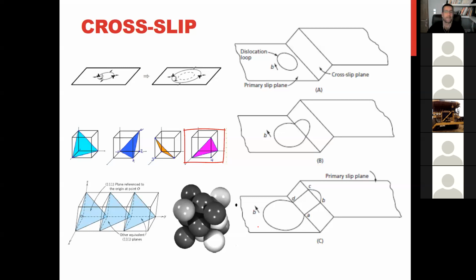Let's see. If you have an FCC crystal, for example, this plane, inside of this plane you have a loop like this. The Burgers vector, for example, is in this direction. This is an edge dislocation, negative. This is a positive edge dislocation. Here you have screw dislocations, left hand and right hand. When you apply shear stress, all of them start to move. This screw dislocation moves in that direction, this one in this direction, and this loop expands.